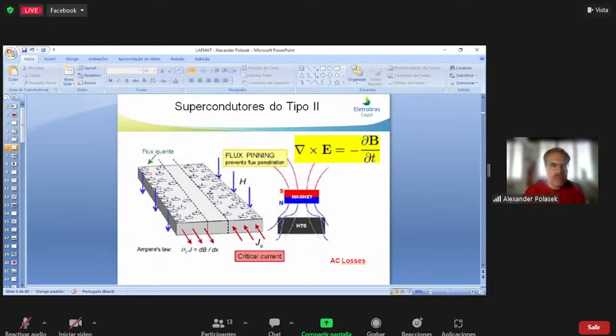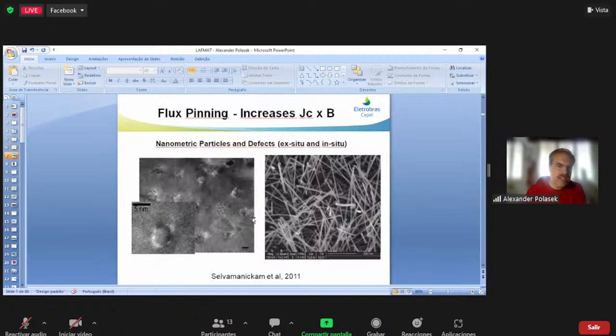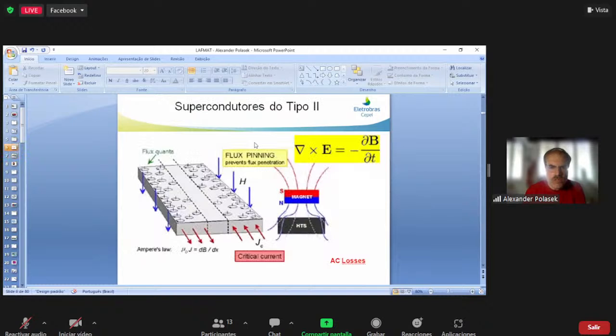And how to prevent it? By using defects or non-superconducting inclusion particles. Typically, you may know very well that these vortices have a nanometer scale. This is the case of high temperature superconductors, but it happens also in low temperature superconductors. You need either nanometric particles or defects to achieve flux pinning.